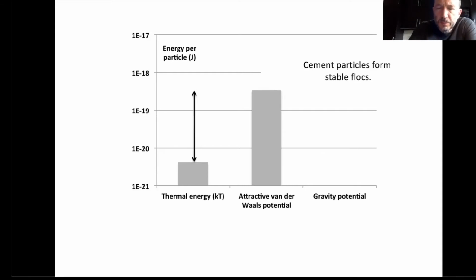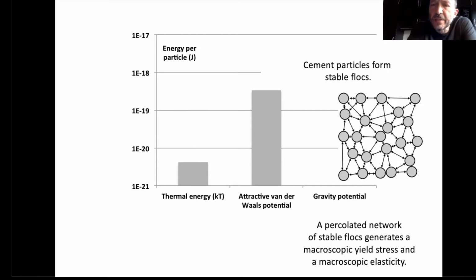In parallel, the attractive van der Waals potential is systematically far higher than thermal energy. So it means that particles will get attracted to each other and form flocs. And these flocs are stable, because thermal energy is not able to destroy these flocs through thermal agitation or thermal dispersion. Finally, if we have enough particles in the system and they get percolated through the formation of these stable flocs, then the system will get a macroscopic yield stress that you will need to overcome for the particles to move relative to each other and for flow to start.